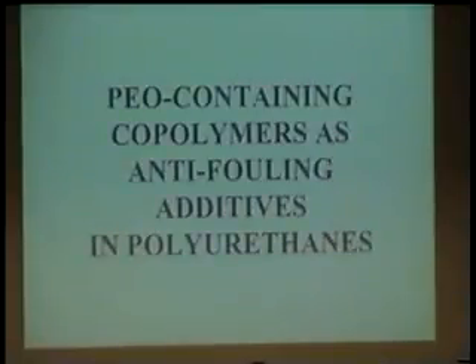Whatever the case may be, I want to tell you now about some work that we've done in this PEO area, which is not grafting the polymer onto the surface, but rather using polyethylene oxide containing copolymers as additives in polyurethane. So we just mix this copolymer component into polyurethane, standard polyurethane as a matrix. And that turns out to be anti-fouling.